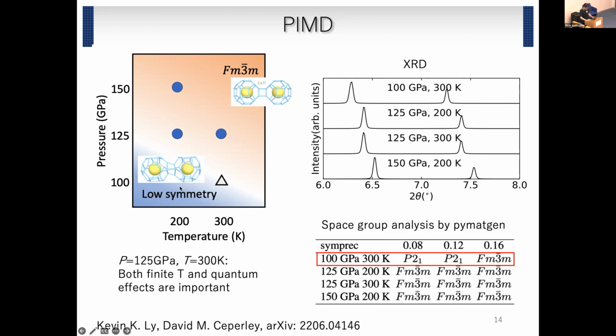So from this result, we can say that at 200 Kelvin, for which there is high superconductivity, maybe both the temperature effect and the quantum effects are important to stabilize the symmetry. But for 300 Kelvin, when the pressure is higher than 125 gigapascal, only finite temperature can stabilize the symmetric structure.